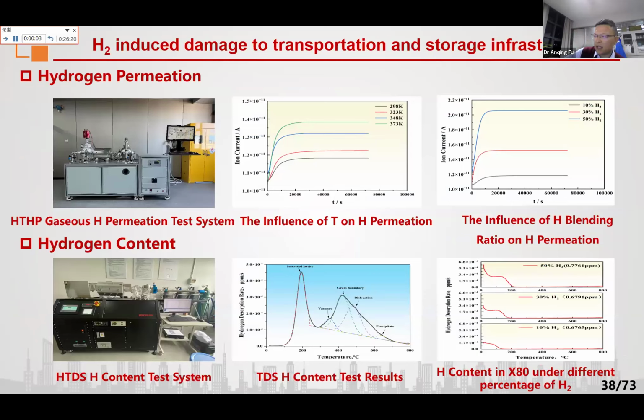We have also done the gaseous hydrogen permeation test under high temperature, high pressure conditions, and how much hydrogen went into the pipeline steel after the test in the gaseous hydrogen environment was quantified by the HTDS method. Actually, those three facilities are not only suitable for pipeline steel or tubing, they are also suitable for aluminum, titanium, stainless steels, as well as CRAs.